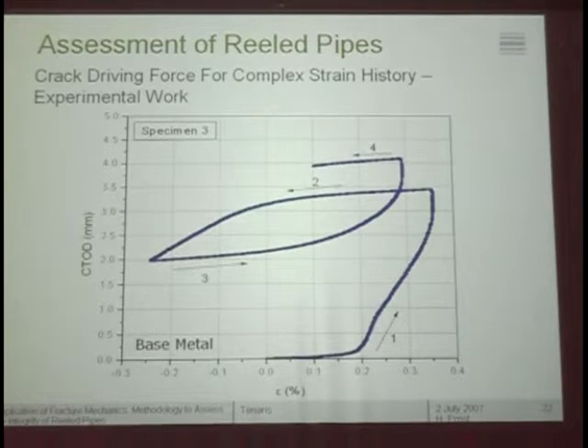deformation cycles. If we were to plot the CTOD measured, physically measured from the size of the specimen, versus the remotely applied strain, this is the type of behavior that you will see.